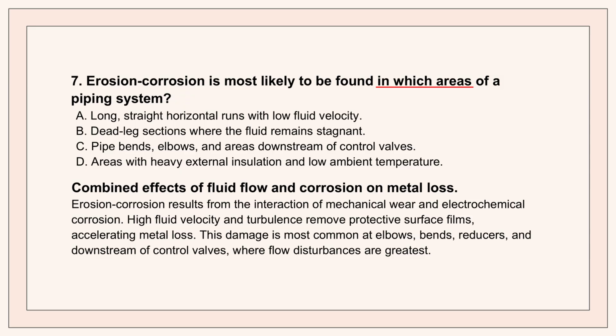So pipe bends, elbows, and areas downstream of control valves. And why those specific spots? It's because the high velocity and the flow disturbances physically disrupt and remove the thin, passive surface films the metal relies on for protection. They're scraping off the armor. You are. And once that film is physically scraped away, the naked metal underneath is immediately exposed to the corrosive fluid. The chemical reaction just accelerates dramatically.